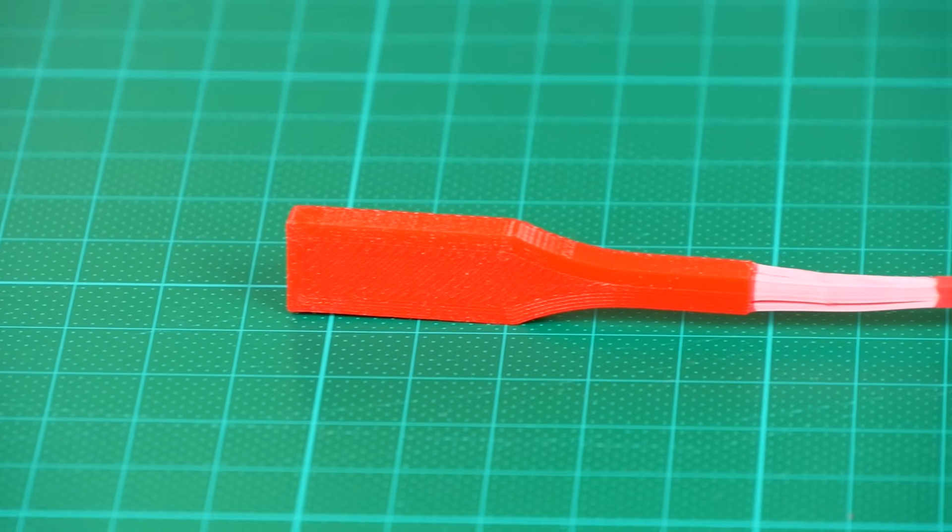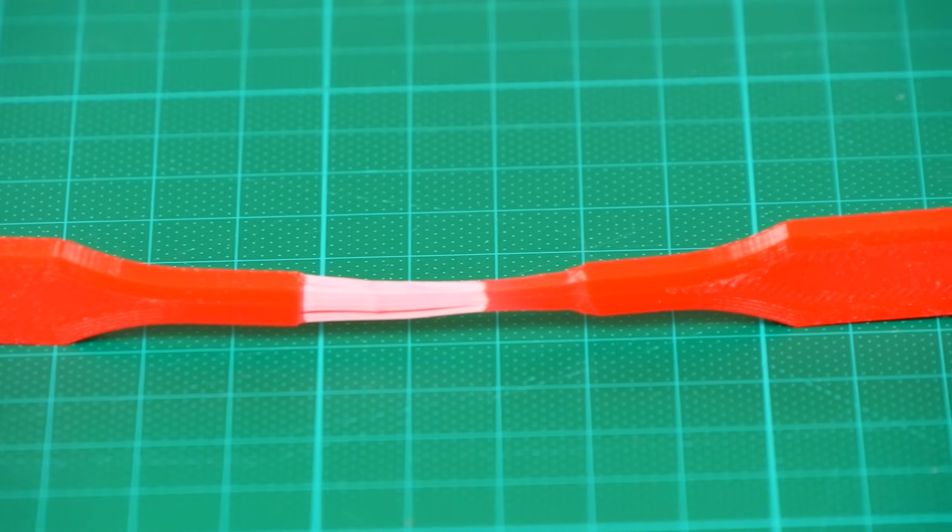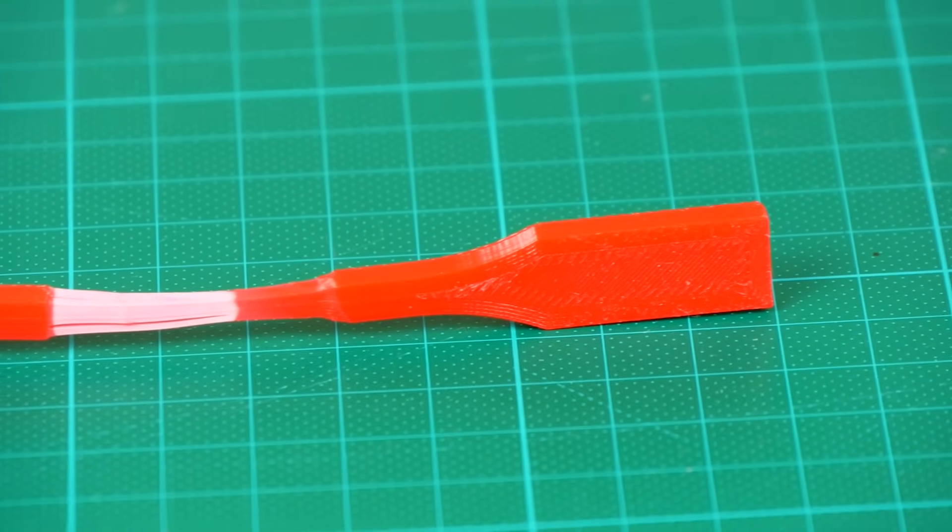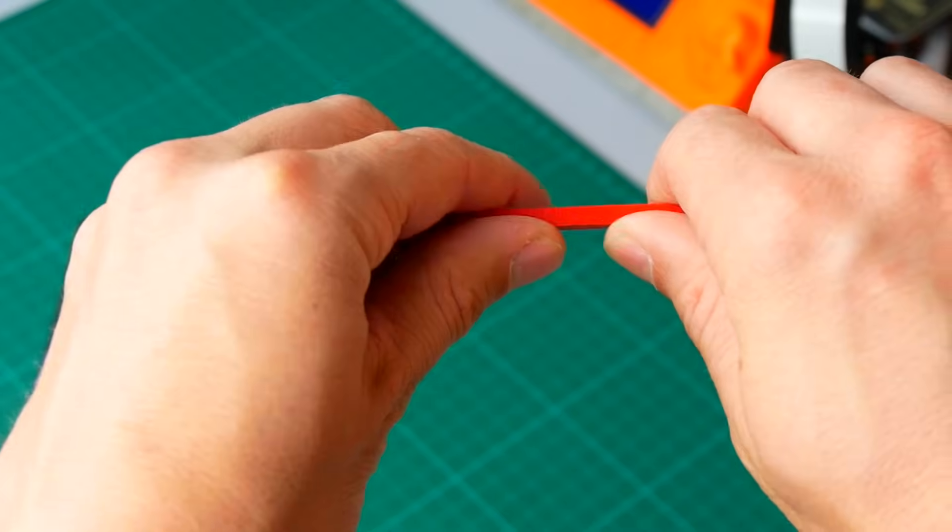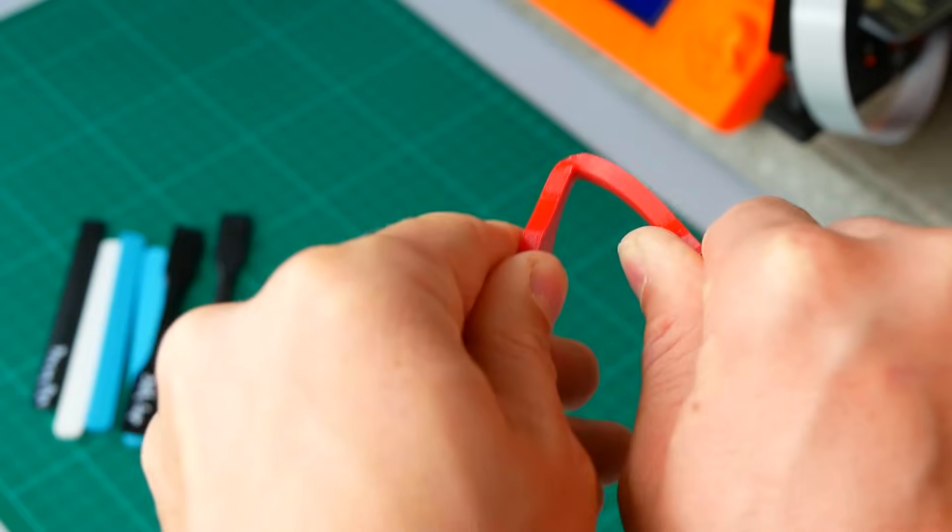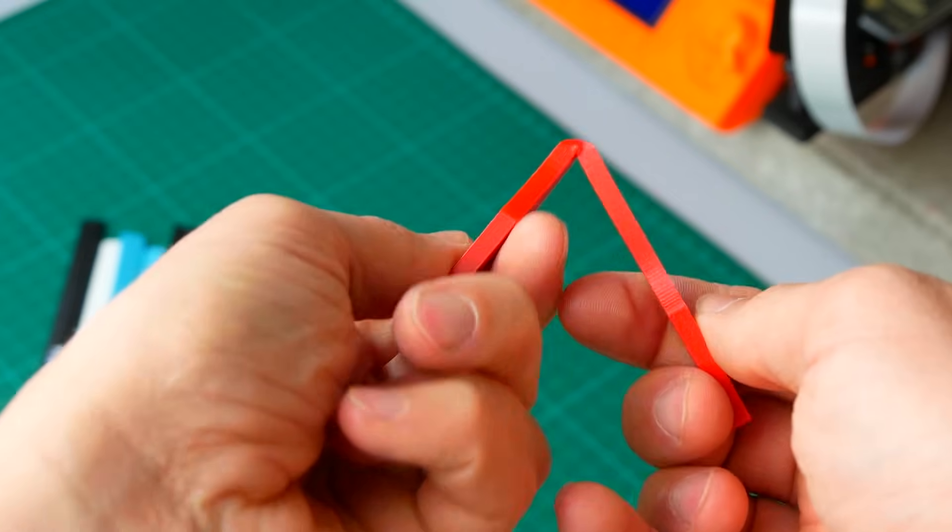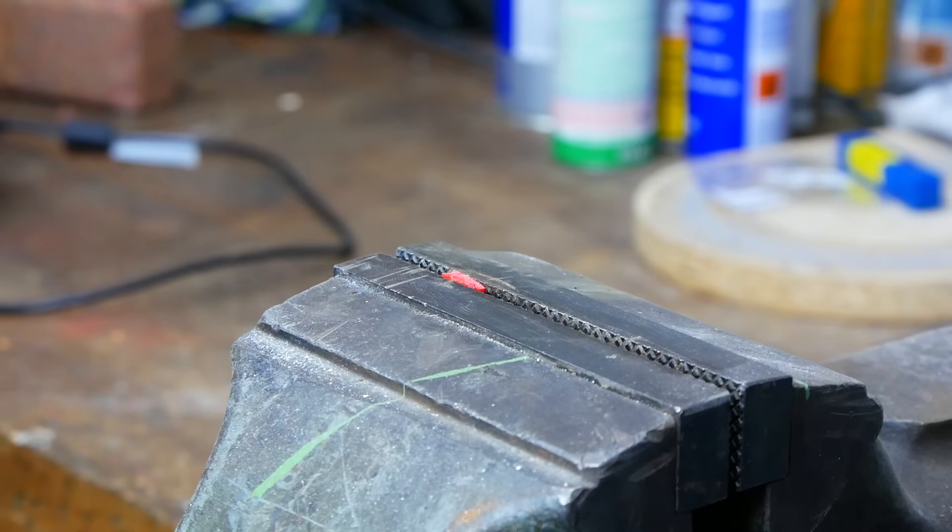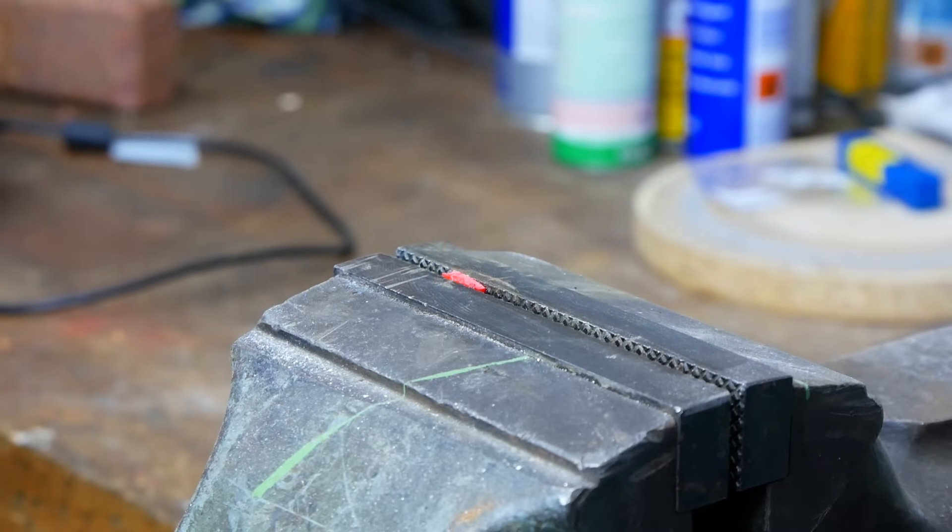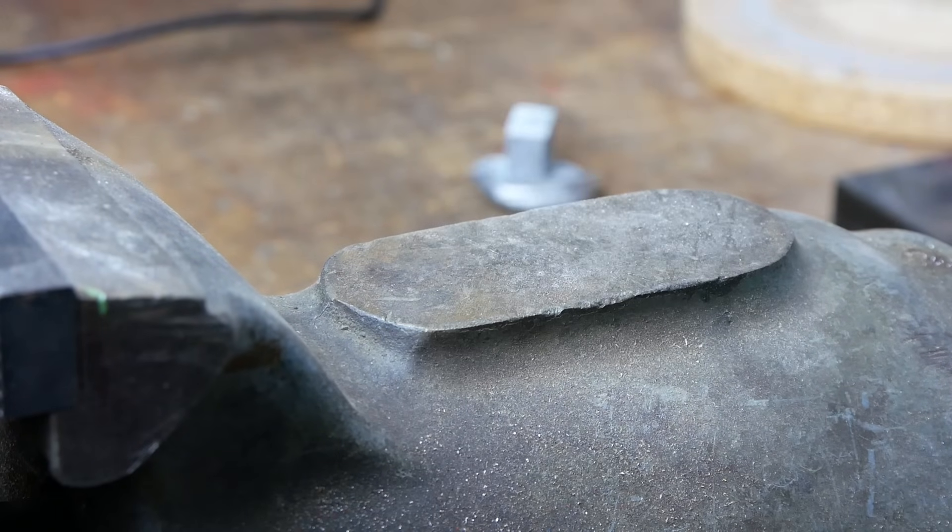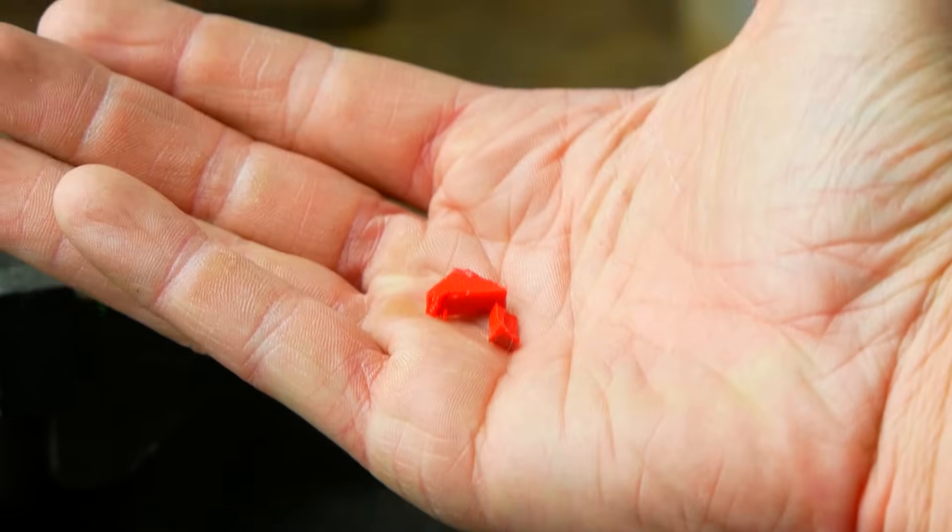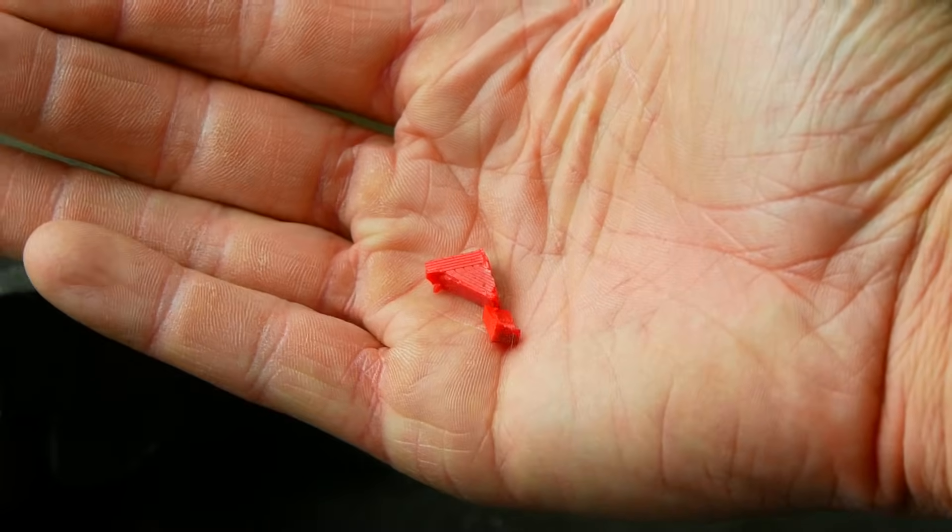One thing which still confuses me is the fact that the material is very ductile if you slowly load it in the direction of the filament strands. I was not able to break one of the specimens because they just strained and strained. Also if you bend a specimen by hand, it will only deform but not break. Everyone who has already worked with PETG will know that it usually behaves quite brittle, actually even more than PLA. I'm no polymer expert, so I don't know if this has something to do with viscoplasticity, but if you load a part with an impact force, like with a hammer, it will shatter into small pieces without any sign of plastic straining. If anyone can explain that behavior to me, I would be really happy to know. I am thinking about building an impact testing machine, maybe then I can also compare these parameters.